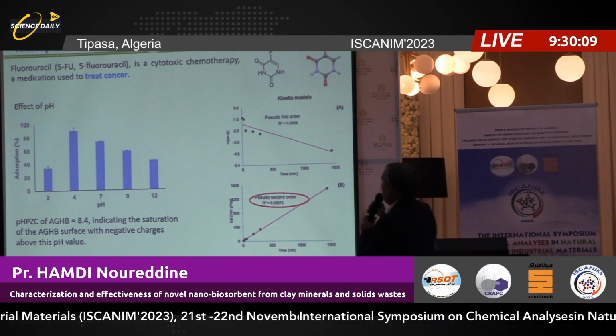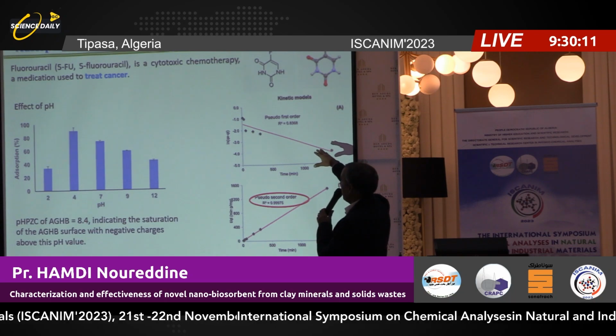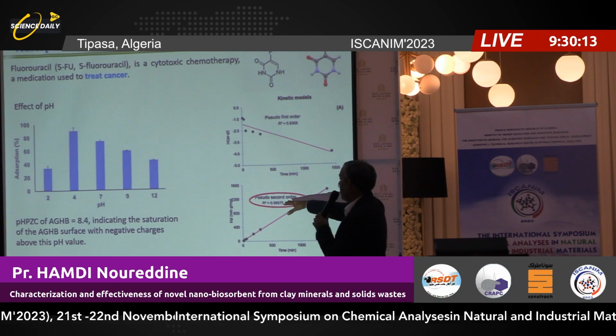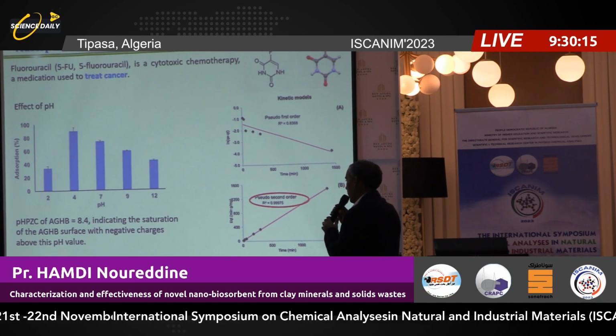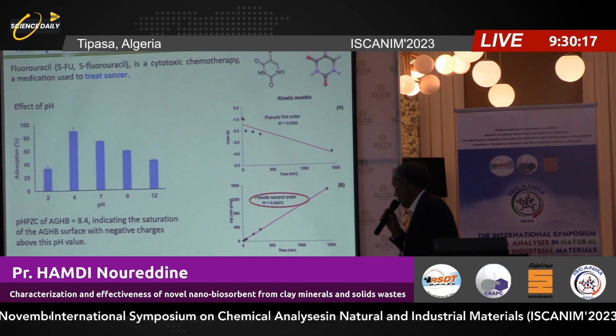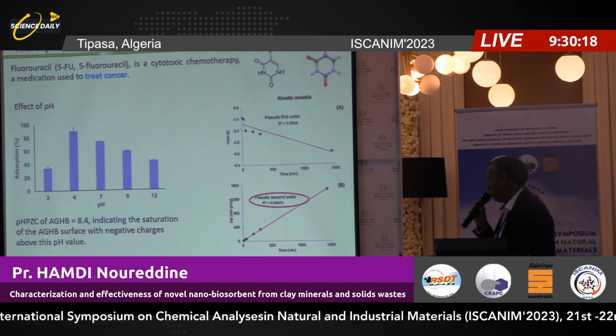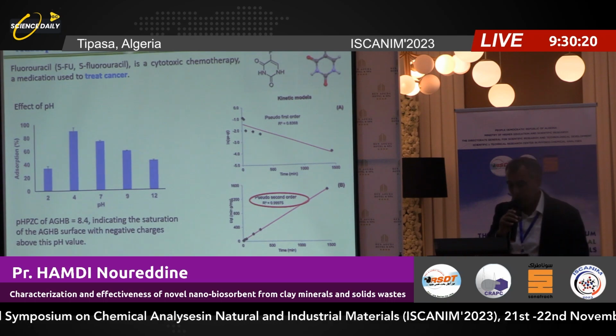Here is the modelization of kinetic by first order and second order. The second order is the best because the R squared is about 1 and the kinetic is very, very fast, about 70% in 1 hour.